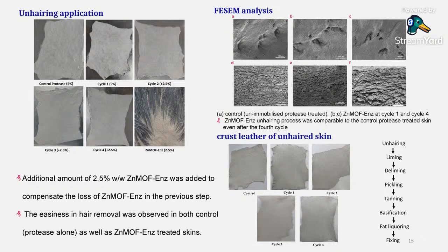The reason is that at each step we are losing some ZnMOF-Enz during the process, because it has a lot of air, so it goes inside. When we wash also, it is not moving out. So there is a loss. So for each cycle, we add 2.5%, but we recycle the first addition of the ZnMOF-Enz. Up to cycle 4, we could see the complete removal of the hair from the skin.